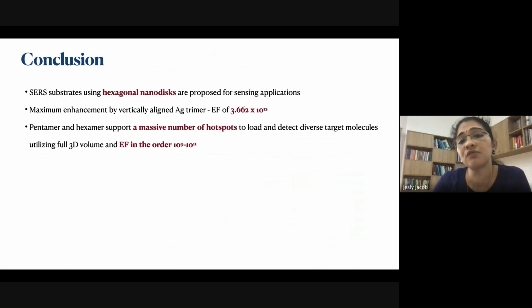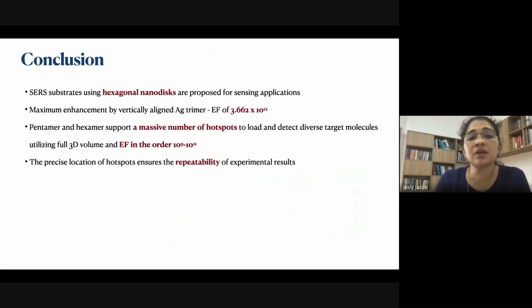has a massive number of hotspots, which help us to load and detect diverse target molecules utilizing the full 3D volume. And it is not much less. Its enhancement factor is of the order 10^9 to 10^11. And the precise location of hotspots ensures the repeatability of the experimental results.